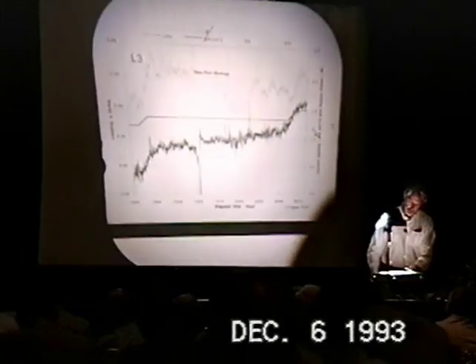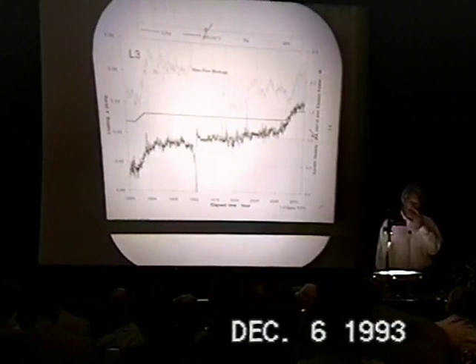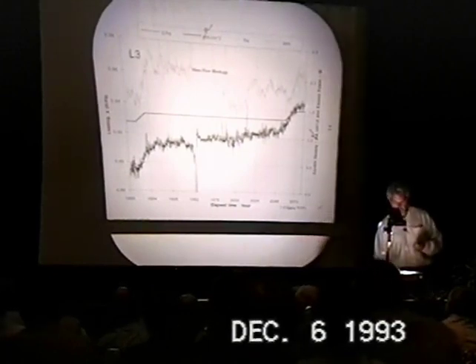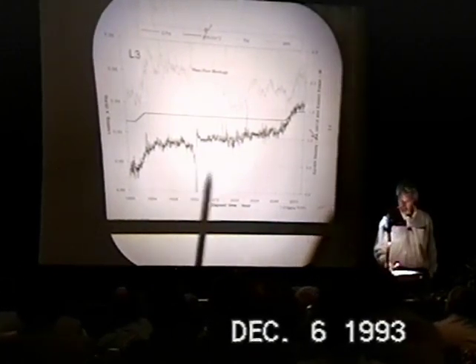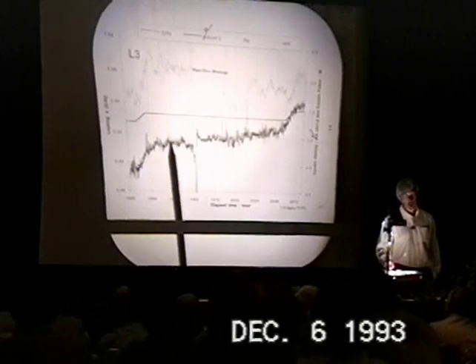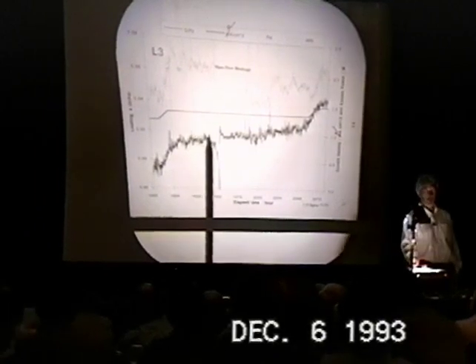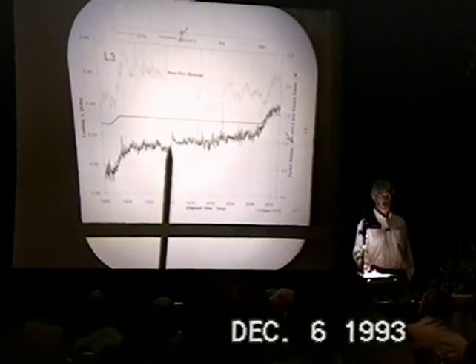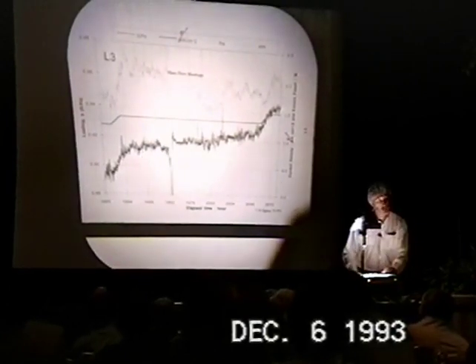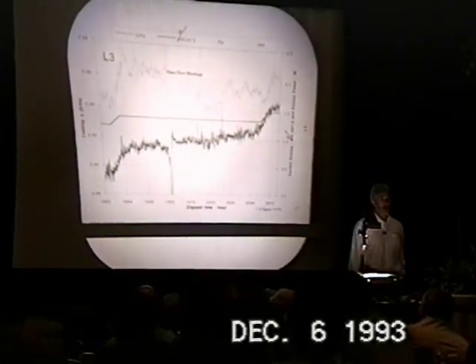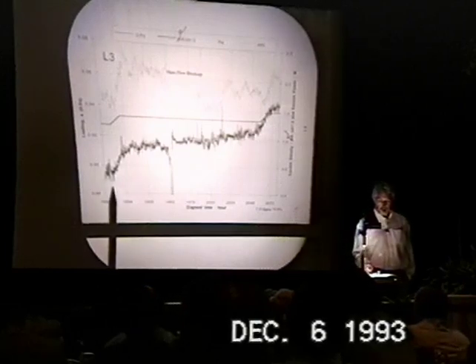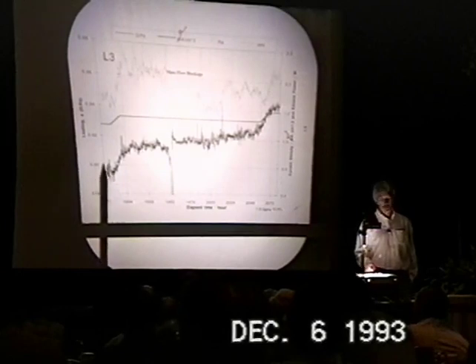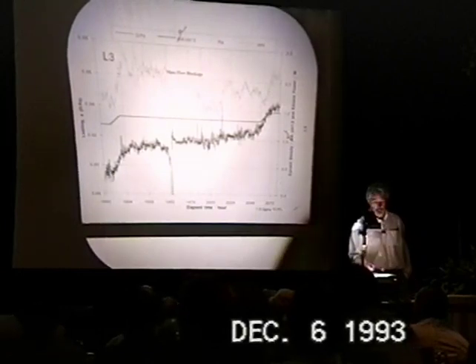Maybe we should pay more attention. One of the other interesting things about this observation, and I see I'm running over time, is that the loading didn't substantially decrease during the time when this cathode got very, very hot. The loading was at a value of a little bit less than 0.9, if you can read these scales.